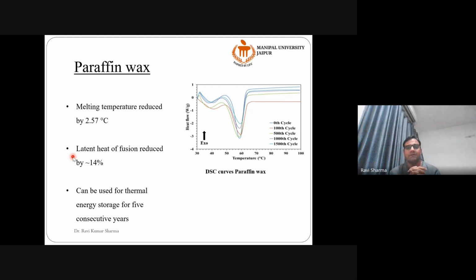For example, paraffin wax - what you can see on the screen are the DSC curves. DSC stands for differential scanning calorimeter curves. This is a machine which tells us the amount of latent heat a material has and the melting point of the material. The melting point of the material we can see at this point, because this is the point where melting starts, and then the melting continues and ends here.